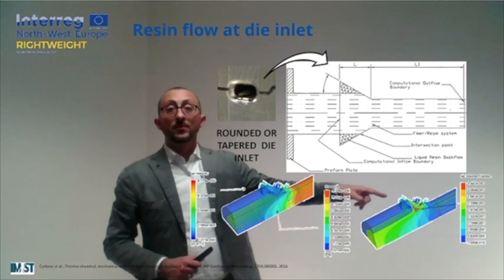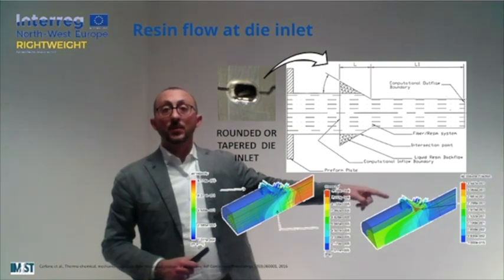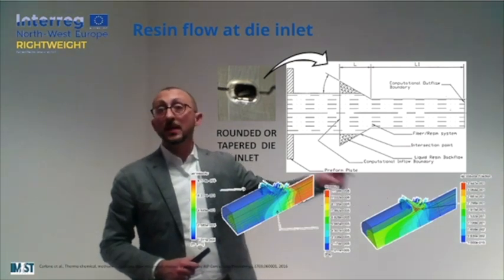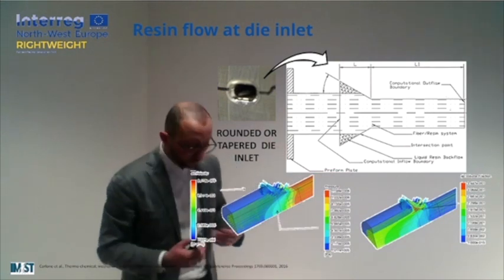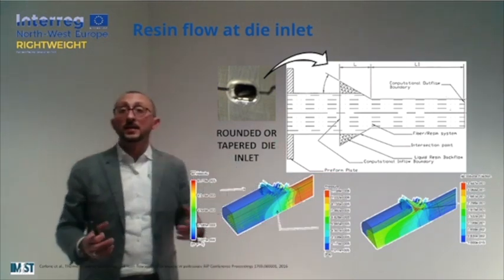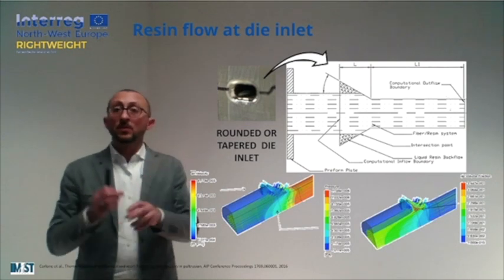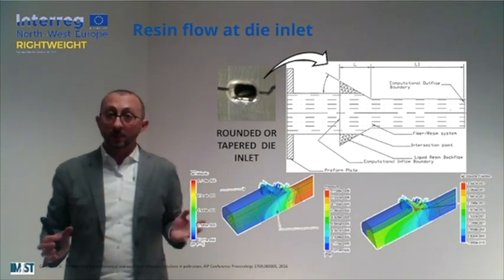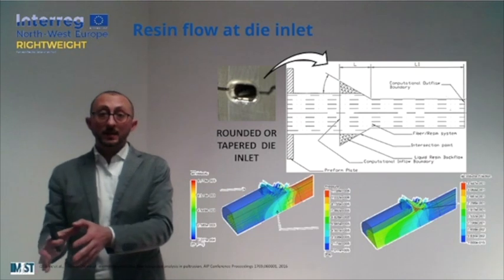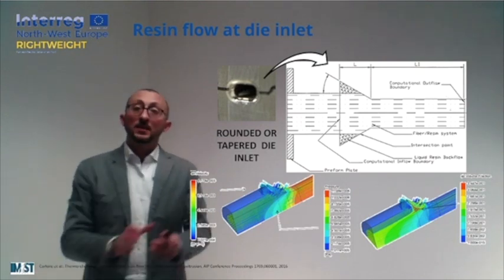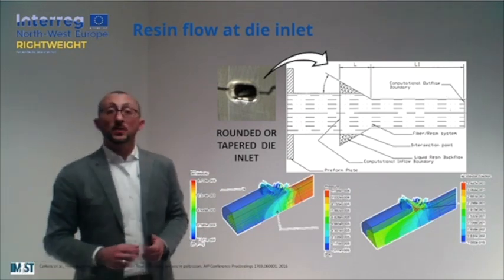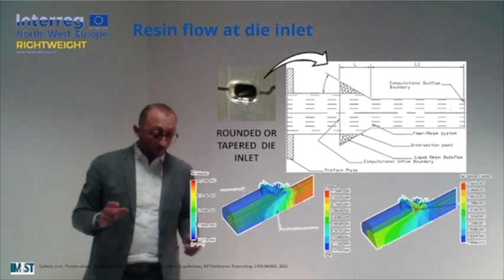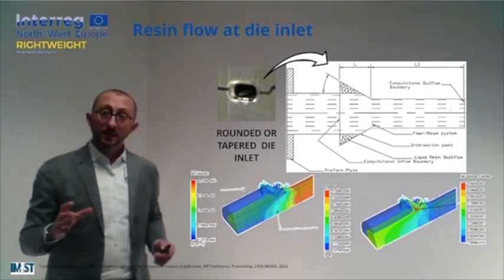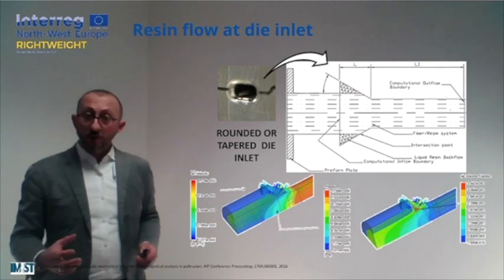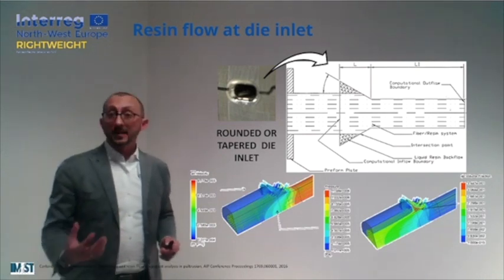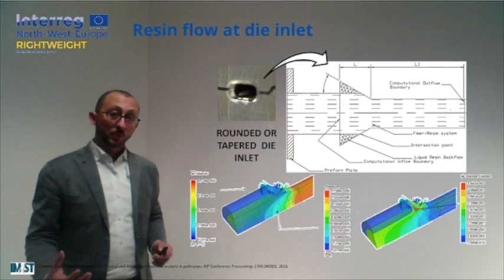So the air volume fraction is the red spot that is there, and typically around the tapered die inlet, it is quite common to see all these bubbles that are flowing away. And we are very happy in that case, because it means that the air is not going inside our cross-section. Now, more or less the same result can be achieved using an alternative to the open bath pultrusion.